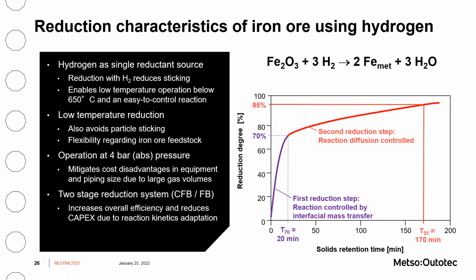The 2-stage reactor setup of first a CFB and a downstream FB is adapted to this reaction characteristic and optimized in regard to the residence time requirements, with minimal reactor sizes and hence minimized capex as a result. As mentioned earlier, hydrogen is an enabler for the fine ore reduction, lowering reaction temperatures and omitting sticking.